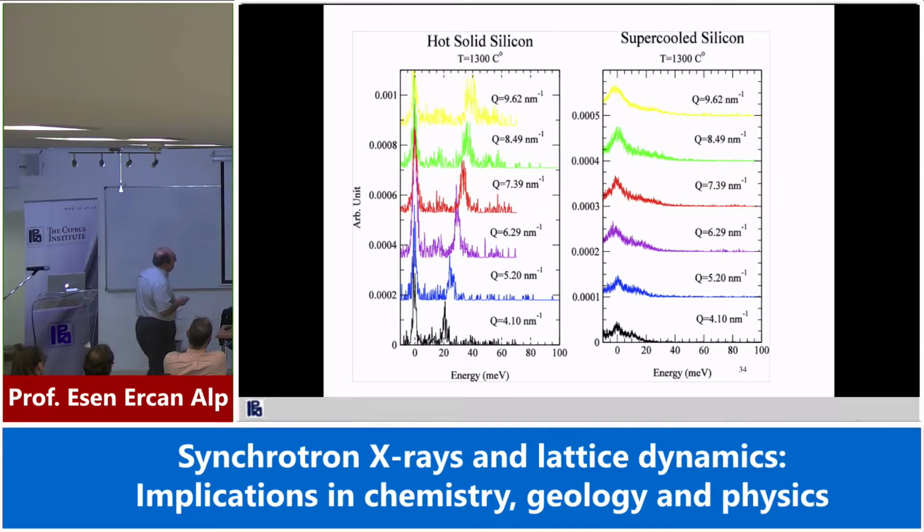So how can I get supercooled silicon? If the melting temperature is above 1300 degrees, you can take a crystal of silicon suspended in air or in argon atmosphere, you send a laser light on the top, and then you wait and heat it up at any temperature you like. We can go as high as 4000 degrees in the lab. All right? And then, since it is containerless, you can cool it down and avoid the nucleation, and you can go down to a supercooled liquid.